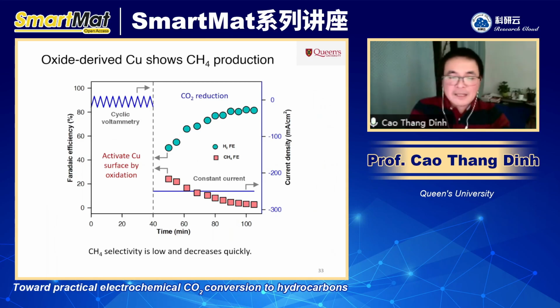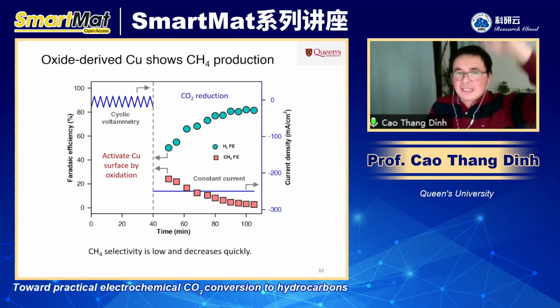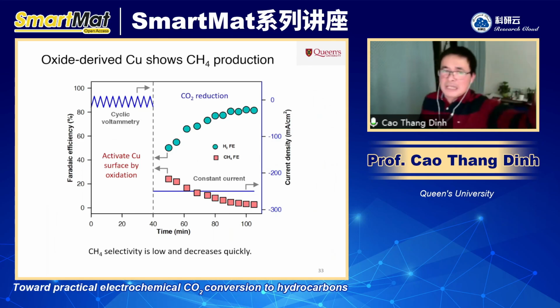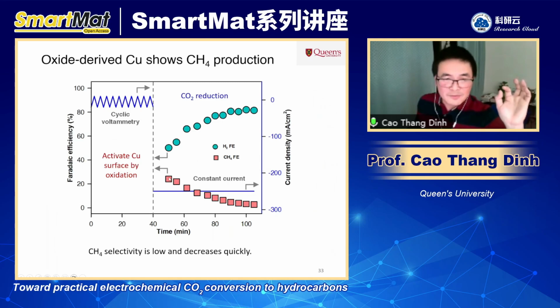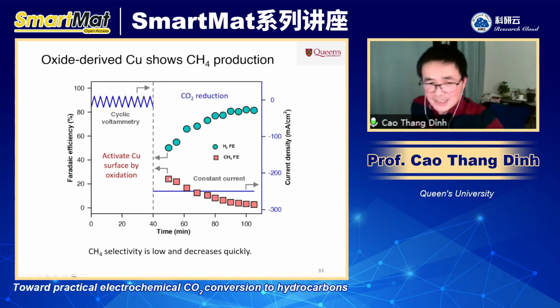In the first 40 minutes, we do the oxidation of the surface. We apply constant CV between negative and positive current so that we oxidize the surface of the copper. After 10 of those cycles, we stop, and then we start the CO2 reduction. Now we start seeing methane formation. From zero methane, now you have more than 20% selectivity for methane.